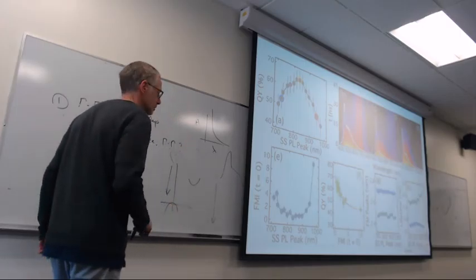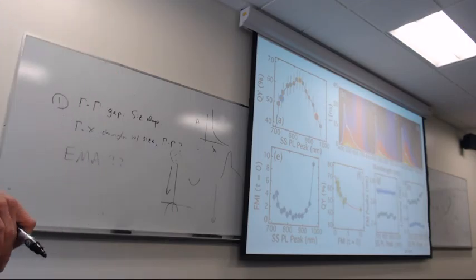No, but I guess you probably say that this mixture with surface states or something like that might be changing the picture, or may help to lift the selection rules. Yeah, because you still have a very strong confinement here, so the wave function is spread over the surface anyway, and then it feels the surface, and then it feels confinement, and then it feels defects. Your indirect gap should also be coupled to this confinement and surface states, and this changes the selection rules, becoming bright rather than dark, as in bulk.